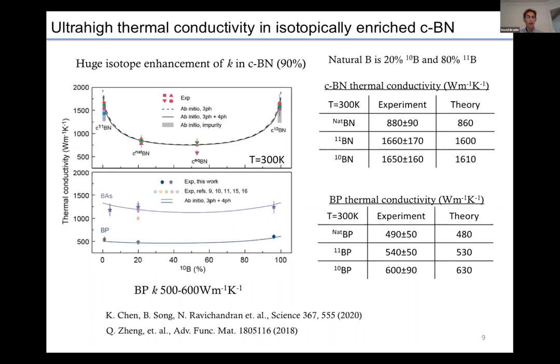And so the top plot is showing our measured and calculated results for a collection of boron nitride samples in which the isotope mixture is varied on the boron atom. And so you can see at the 20% mark, the naturally occurring boron nitride has thermal conductivity that's quite high, approaching 900 watts per meter Kelvin, higher than what was measured in earlier work that I presented on the first slide. But upon isotopic enrichment, where we make either almost 100% boron 11 or 100% boron 10, so at either end of the curve in the top plot, you see the thermal conductivity increasing dramatically, almost by a factor of 2 to over 1600 watts per meter Kelvin.